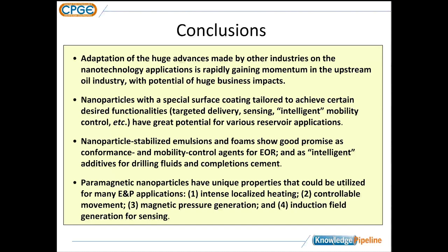Yeah, so that's a good question. A lot of this has to do with the degree to which the nanoparticles repel or attract each other. And that depends somewhat on the surface coat. So if you have nanoparticles that have a negative surface charge, if you add cations in there, it's actually going to pull them towards the cations, and they might end up agglomerating a little bit. On the other hand, if you have more of a neutral surface charge or a positive surface charge, that effect can be equalized somewhat. And actually what we've seen is that effect isn't the same for every nanoparticle. Some nanoparticles will tend to agglomerate when the salinity increases, and some of them will tend to maybe get separated a little more when the salinity increases. So it's actually a pretty complex phenomenon which has to do with the interactions at the molecular scale.